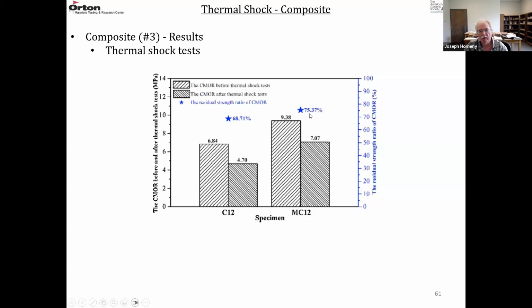It retains 75% of its strength after thermal shocking. C12 only retains 68%. But you can look at the difference here. After thermal shocking, it's what's really important. This strength is much higher, actually, than either one of these strengths before and after thermal shocking. So what we predicted, MC12 should be better, and it actually is in these thermal shock tests.